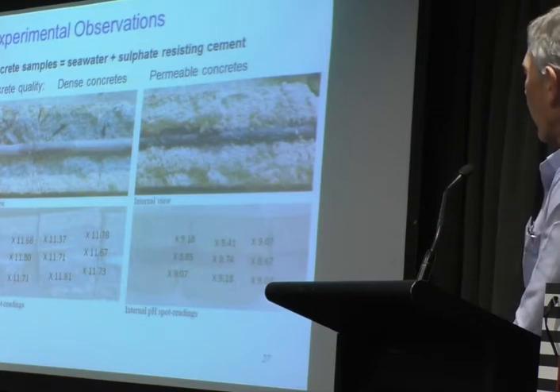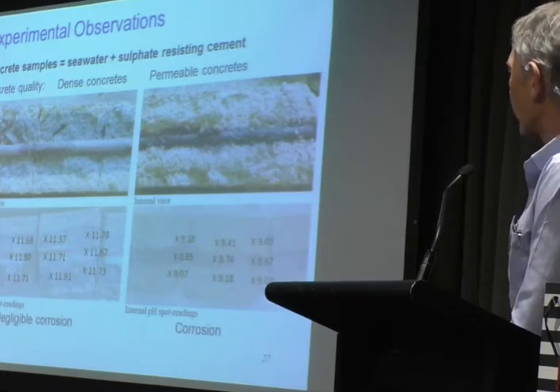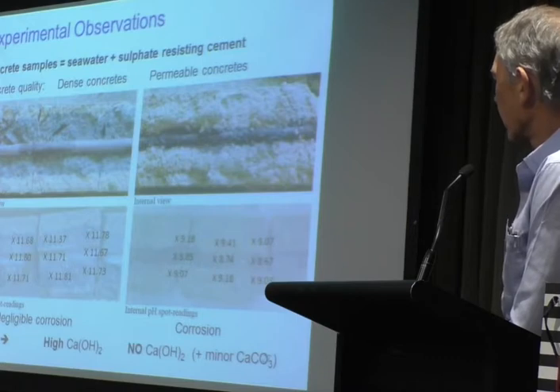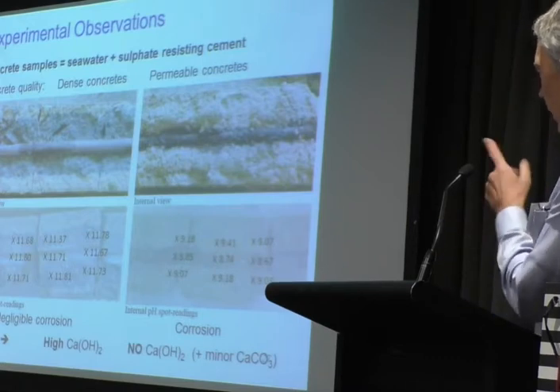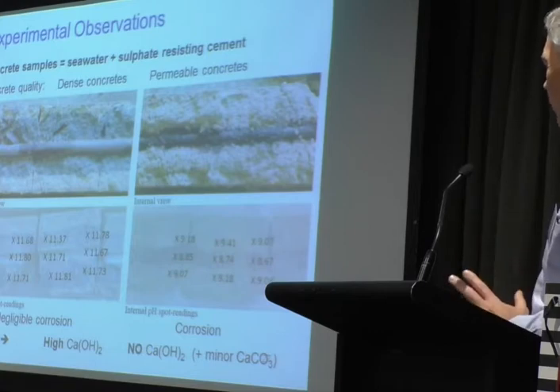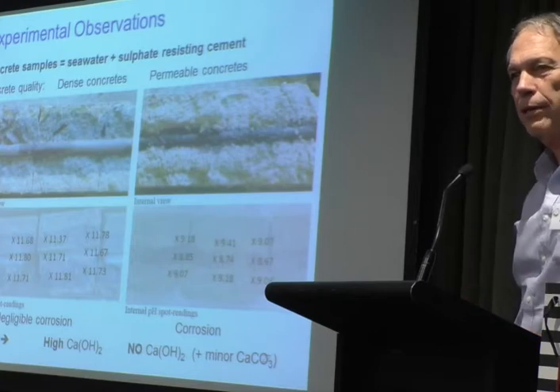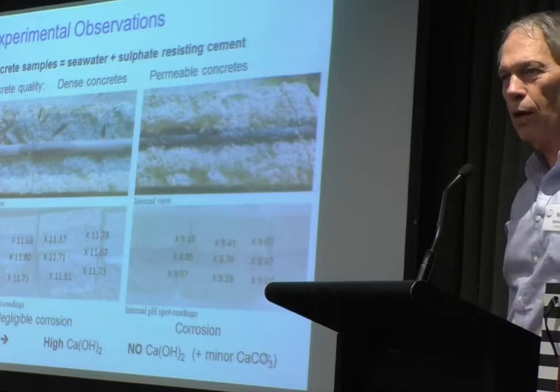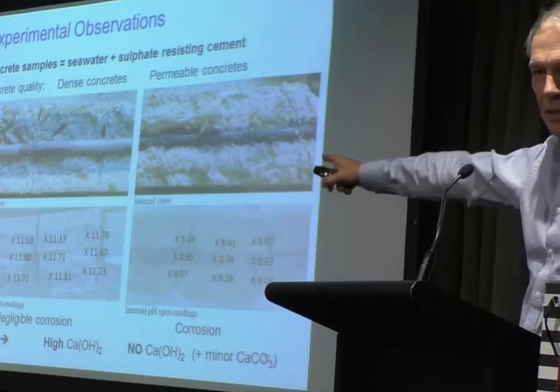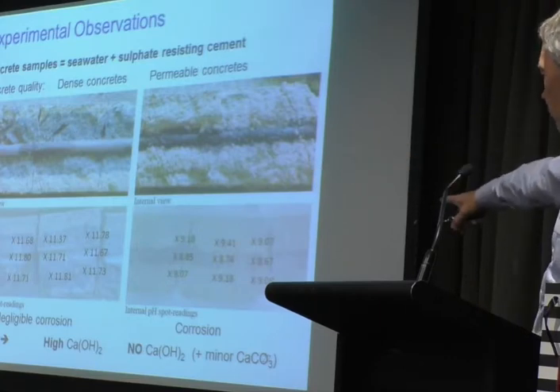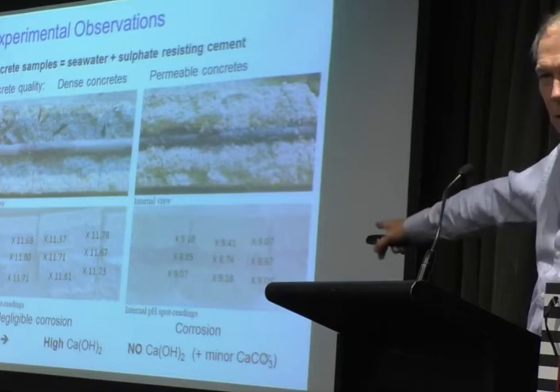We then started to look at what is actually inside the concrete. And we did that by various techniques, including XRD and EDS and so on. And to cut the whole story short, the ones on the left still had a lot of calcium hydroxide in the mix. They were still quite alkaline. And they would have been because of the pHs. And the ones on the right, there was virtually no calcium hydroxide left.